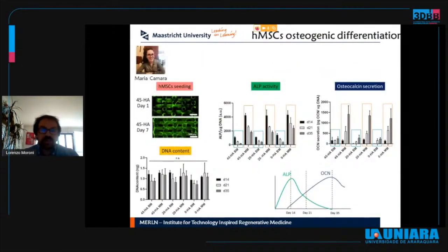What we saw in vitro is that, again, these kinds of scaffolds induce a high amount of alkaline phosphatase activity, which is an early osteogenic marker, but also the increase of more mature proteins such as osteocalcin, which is further expressed typically at later time points. So in the course of 5 weeks of culture.